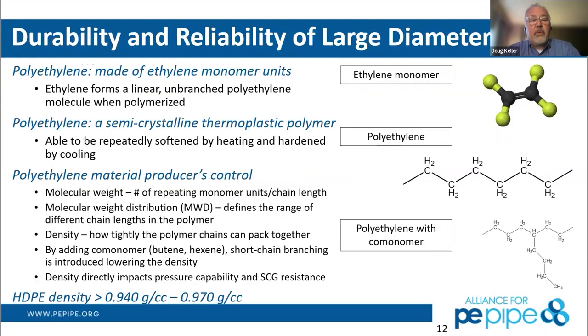So as a polyethylene manufacturer, what I control is the molecular weight of the material, so how many of those ethylene units I string together. The molecular weight distribution of the material is also something that I have control over. We don't make chains of exactly the same length. We have varying lengths of the chains because it provides different properties for us. And then we can also adjust the density of the material by adding co-monomers. Those co-monomers are typically butene or hexene. What they do is they go into the linear chain, which you can see in the middle. And when I put a co-monomer in, which is down on the bottom right corner, that co-monomer disrupts the crystallinity, the crystal structure of the material, which allows for a lower density. So the more co-monomer I incorporate, the more I can change the density. High-density polyethylene as a material is typically between 0.940 and 0.970 grams per cubic centimeter. Next slide.